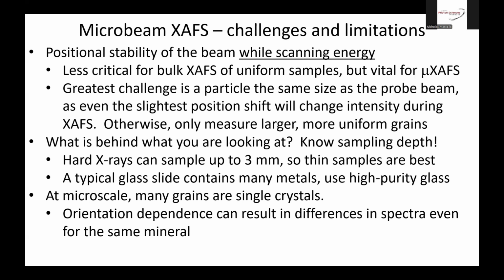The greatest challenge is if there's a particle the same size as the probe beam. If it walks the slightest bit, it'll walk off the particle, and your spectrum will do all kinds of crazy things that won't be very useful. So you have to find larger grains or more uniform areas of samples and make sure that you accommodate that. It's also important to think about what's behind what you're looking at. When you're looking at very small things, the sampling depth of the X-rays, especially hard X-rays, is pretty deep. It can be hundreds of microns or even millimeters. And so you have to be aware of what's behind your sample.